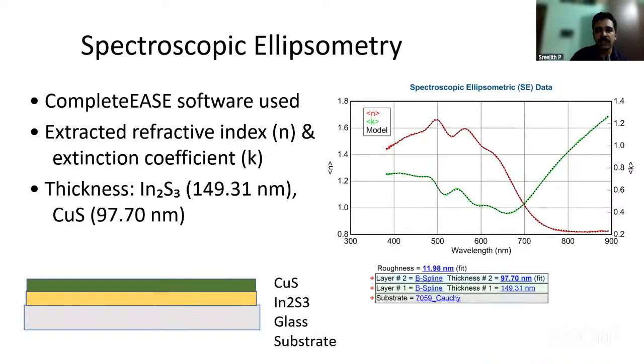Spectroscopic ellipsometry measurements were carried out and analyzed using CompleteEASE software. From the ellipsometric data, the refractive index and extinction coefficient were extracted. Ellipsometry analysis of the bilayer structure yielded a thickness of approximately 150 nanometers for In2S3 and 100 nanometers for CuS, confirming uniform film growth.